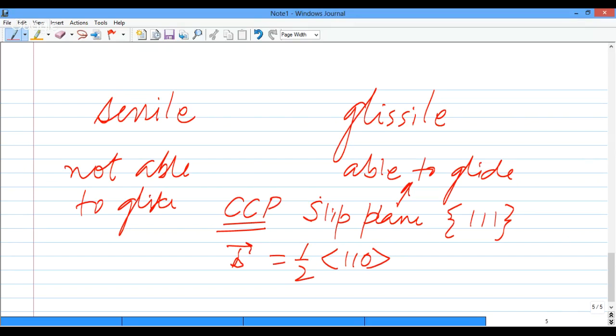Shrikant sitting here is correcting me that it should be bar 110 to make him happy. Let me put this bar 110 to satisfy Weiss's law with the plane written here. But since this is a grouped thing, we are always knowing that we can select a suitable one. So this will be glissile. But suppose a dislocation line with the same Burgers vector is now lying on a different plane, a 100 plane. Then that dislocation will become sessile, because the 100 plane is not a favorable slip plane. In other words, the critical resolved shear stress required to move the dislocation on the 100 plane is very high. So if it lies on the 100 plane, then it will be a sessile dislocation.